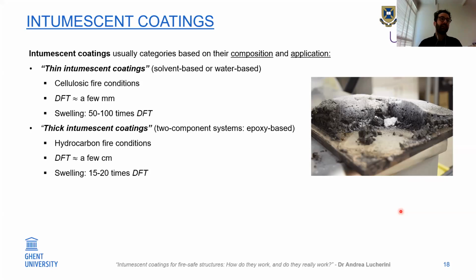On the other hand, there are thick intumescent coatings, also called two-component systems, which are usually epoxy-based, and in this case they are usually prescribed and applied in hydrocarbon fire conditions, for example in the petrochemical industry. In this case, the DFT is usually in terms of a few centimeters, and they swell less, up to 15-20 times the initial DFT.